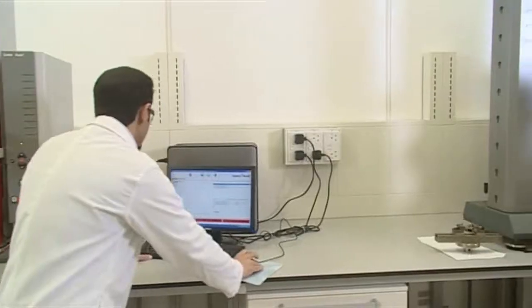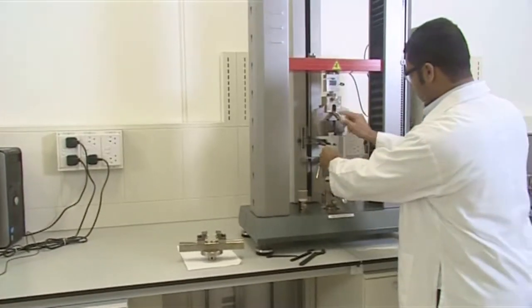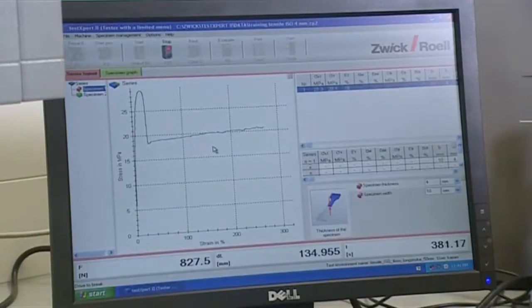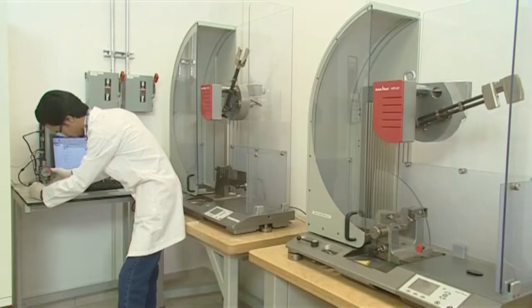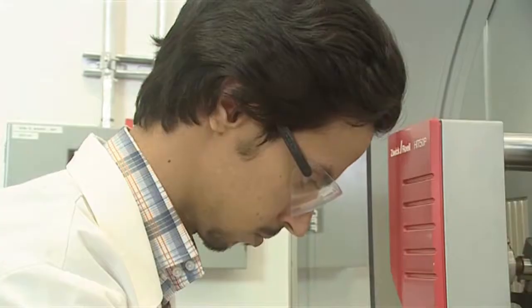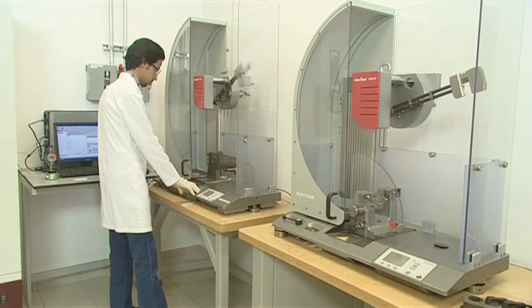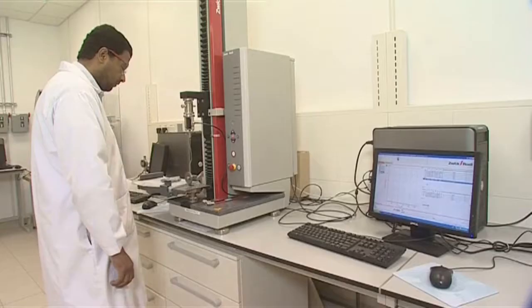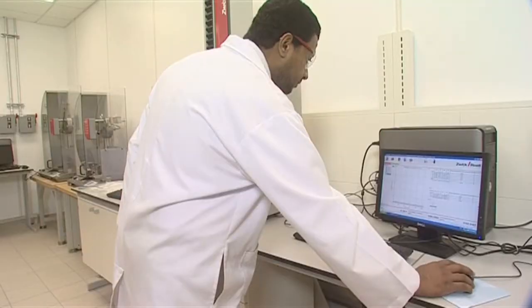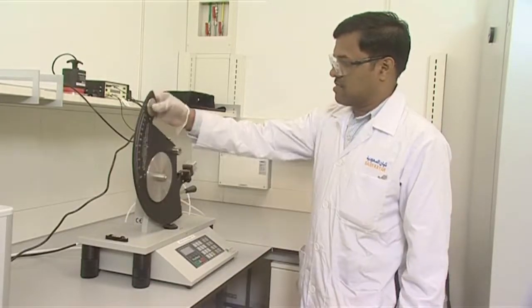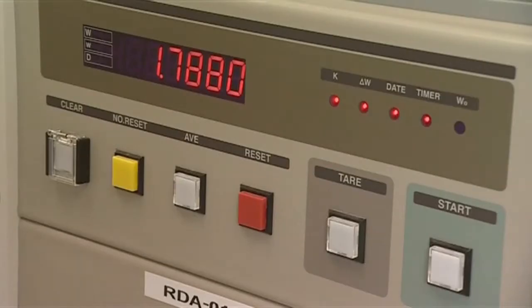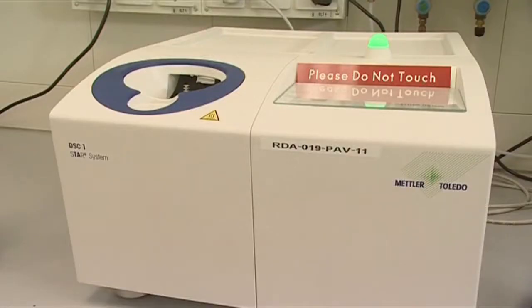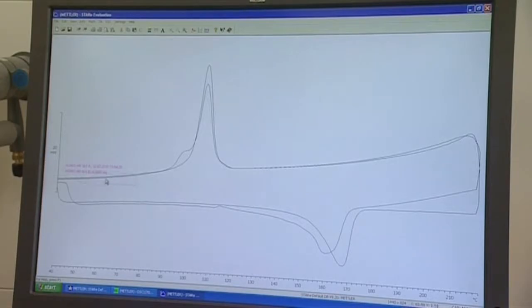Physical properties of the polymer are intrinsic and essential to establish the grades. The tensile machine for tensile and flexural properties. Impact testers for the impact strength. The films are analyzed for coefficient of friction and tear properties. Density of polymer with auto density meter. DSC for the oxidative induction time and crystallization temperature of polymer.